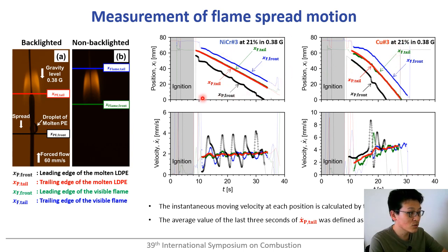Those figures show the typical analysis results for the nichrome and the copper cases. The figure on the top shows the time history of each location, and as you can see, the flame along the nichrome wire reaches a steady state right after ignition, but the flame along the copper sample requires a longer time to reach steady flame spread.